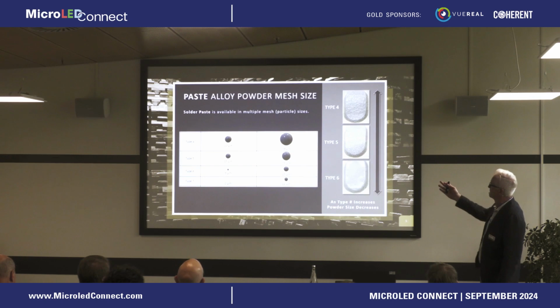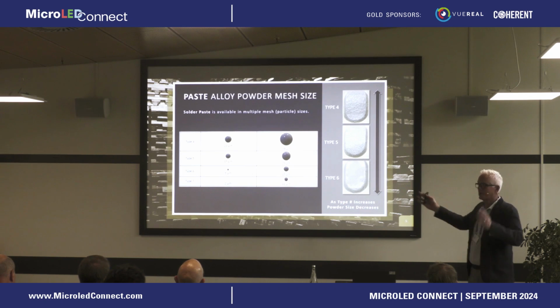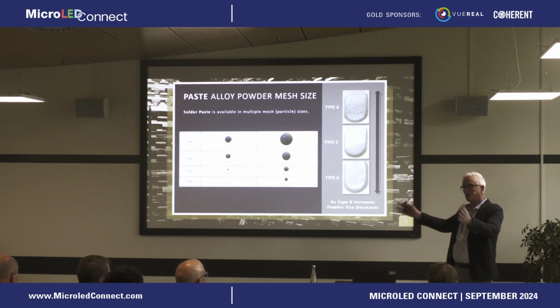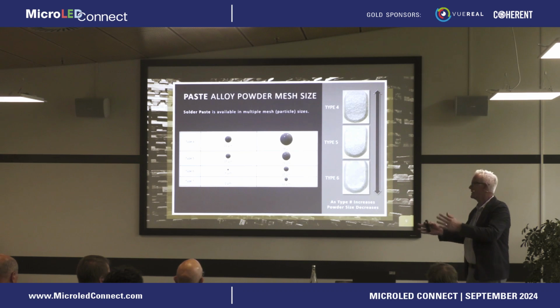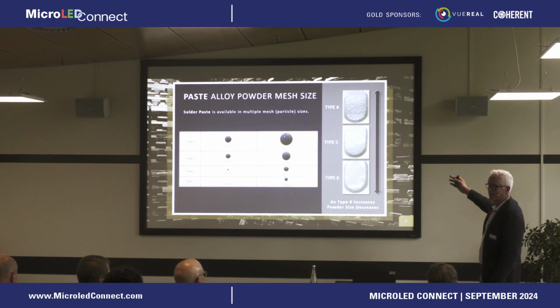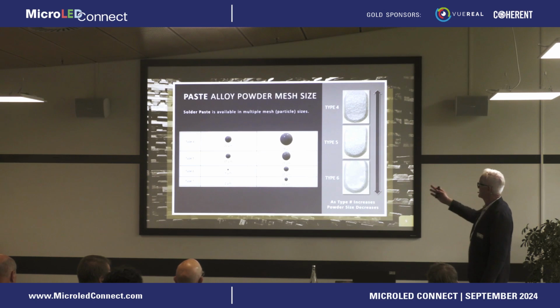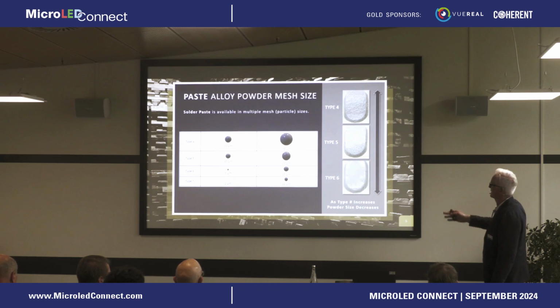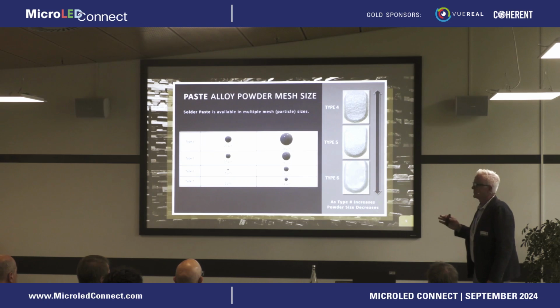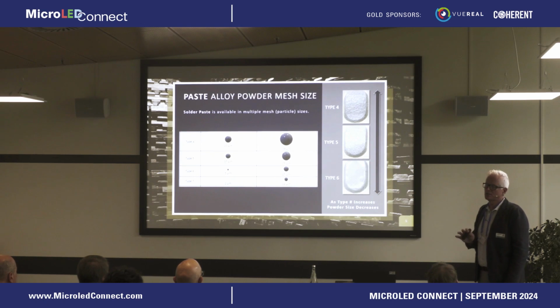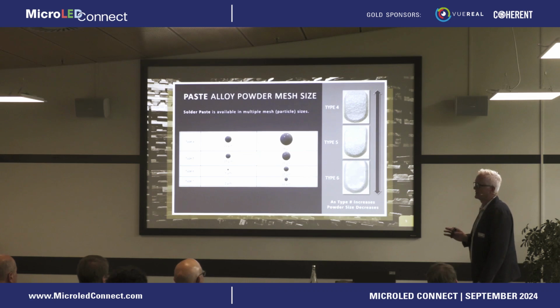And you can see the ratio of the size of the spheres relative to one another in the different mesh sizes. So I have a range. I get to be this big and this small, and I have to fit the powder in between that range in order to assign it a type. And as you can see, type 4 is significantly larger than type 6 and type 7. That's really the tipping point for the technology in terms of reflowing a solder paste successfully.